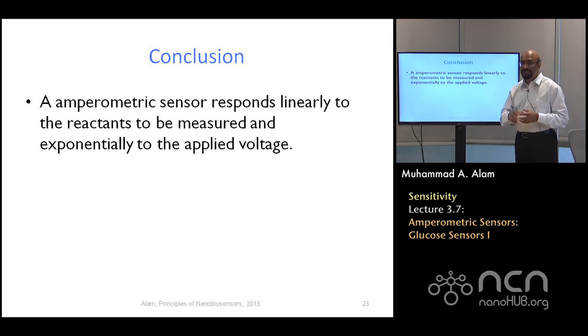And another thing is this KF and KR, the reaction rates, well, that depends on the voltage you apply to the electrode itself. The higher the voltage you apply, the better it is, because then you'll have more current. The two levels will become more and more aligned. However, if you apply too high a voltage, then yes, this current would be large, but there may be parasitic reactions from other levels sitting close by, which will essentially contaminate your signal. These parasitic channels you don't want to activate because that will reduce your selectivity.